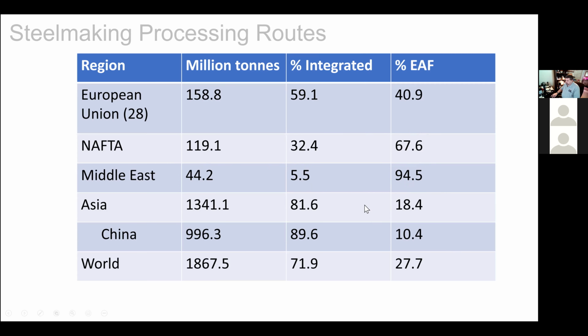And then we see other areas like Asia, not even 20% electric arc furnace. And that's partially due to not really having the electrical power available in a lot of cases. And this is a problem in China, where for this past year they're now up to 12% electric arc furnace based. And then you see the world figures, 28% electric furnace based, but that'll really change. Between now and 2050, you'll probably see that grow to about a 50-50 or maybe even higher.